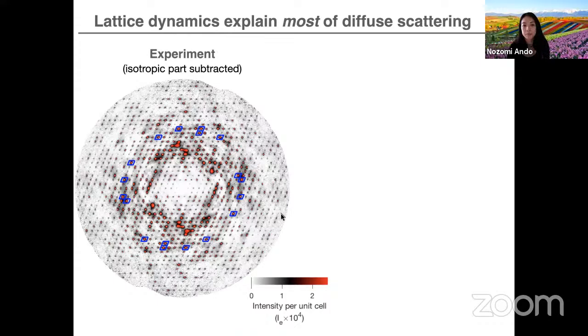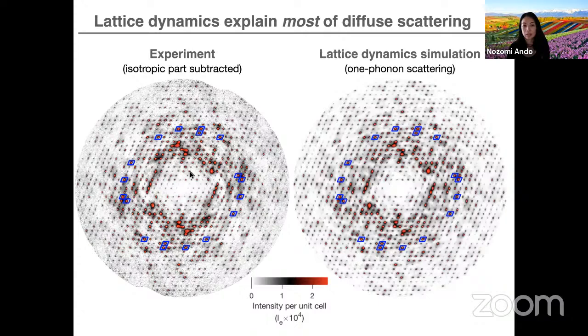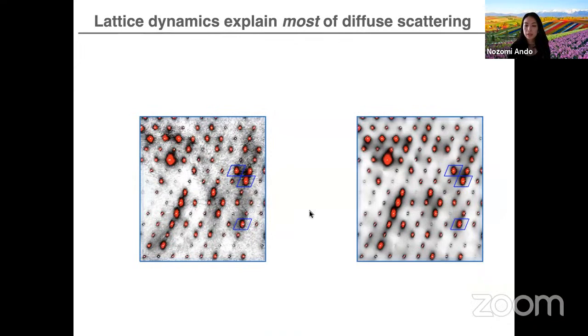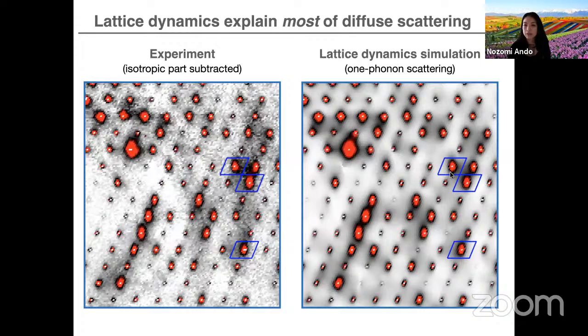But the refined lattice dynamics model does an excellent job of agreement with the data. You could see that it looks very similar. This is probably the best agreement that the field had seen. And if we zoom in here, in this particular region, there are only three halos that were fit, and yet the simulation does a really excellent job.